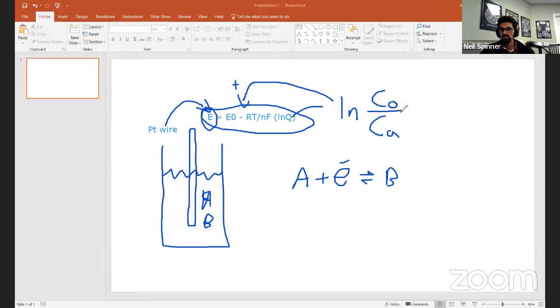But the opposite happens too. You can change the potential by changing the ratio of the concentration of these species. And so when you're doing redox flow batteries, which is the case of Stu, you're able to change the potential by adjusting the ratio of these two concentrations. So that's the important thing.